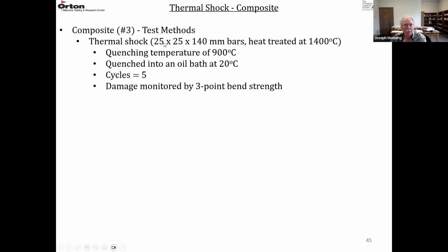These bars that were subjected to thermal shock were the ones that were coked at 1,400 degrees C. So the phenolic resin is pyrolyzed into carbon. Typical quenching conditions: 900 degrees C to an oil bath at 20 degrees C. Samples were cycled 5 times, and then the bend strength was measured to monitor the damage.